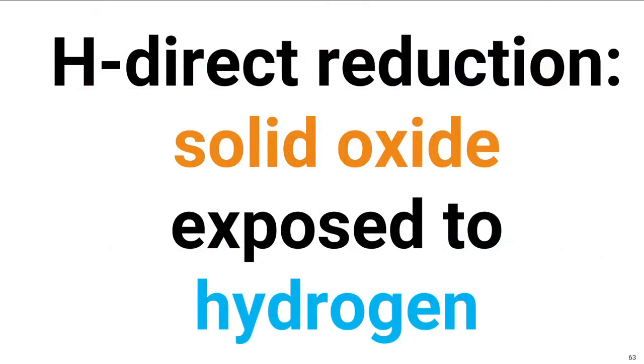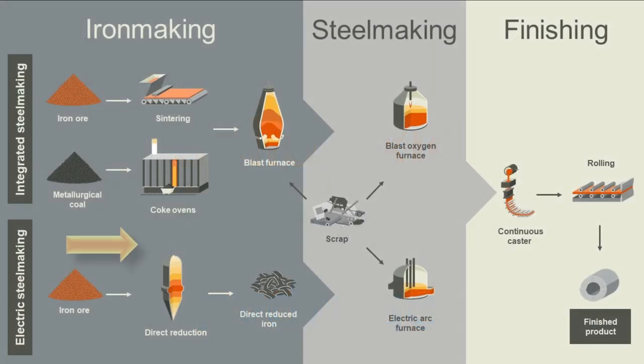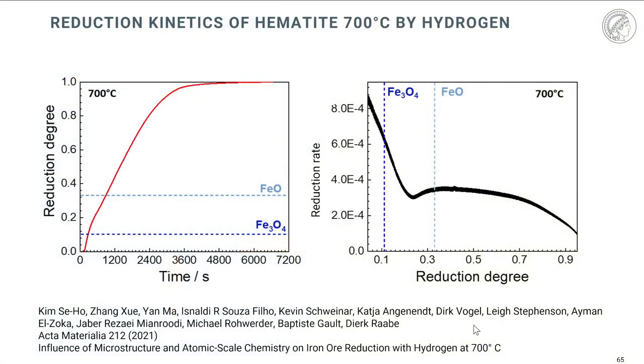Let me show you a few examples about hydrogen-based direct reduction of solid oxides that are exposed directly to hydrogen. This is a typical overview of integrated steel making, and we only look at this part where we use iron ore subjected to direct reduction. However, we use hydrogen and not, like typically, methane gas. And from that we get iron sponge, which is then melted down in electric arc furnaces.